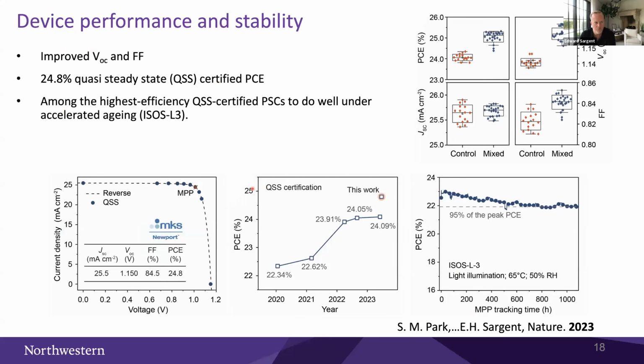So in terms of device performance, this enabled us to report a 24.8 QSS certified PCE, and to do it on devices that also exhibited interesting stability. And so you'll see on the bottom right here, the MPP tracking time going up to 1,000 hours for these devices operating at 65 degrees C and 50% relative humidity, and retaining 95% of their peak PCE at that operating temperature over the course of that 1,000-hour period.